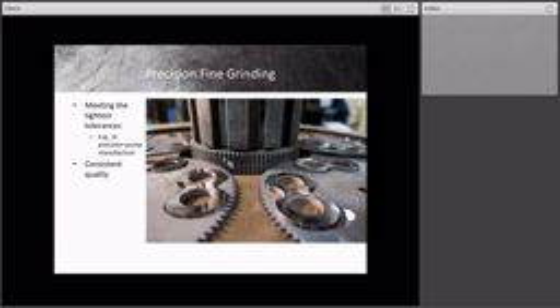The next step might be fine grinding. Now, what you see before you are precision pump plates that are held to about 4 or 5/10,000ths of an inch in tolerance on the length. And those components are fine ground in a machine that's dedicated specifically for their application. Could be used for gears, could be used for pump plates, could be used for gerotors. There's a variety of things that can be done, and it's also capable of lapping. So it's very close to a lapping operation, which is a very fine, very low material removal operation.